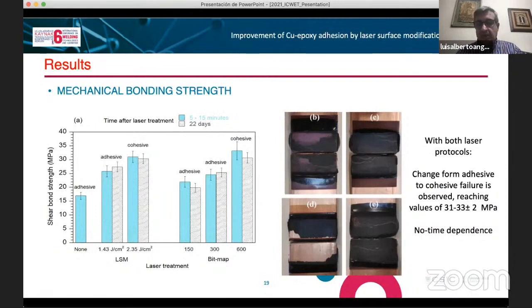We have also observed how the failure of the joint occurred, and we have seen that in the case of the laser scanning mode, when we have low roughness values, the failure is adhesive, and it becomes cohesive at the highest one. We have a similar behavior when we work in the bitmap configuration with 600 dPis. When we have the cohesive behavior, it means that the mechanical properties are limited not by the adhesion of the epoxy with the copper, but by the mechanical properties of the epoxy.